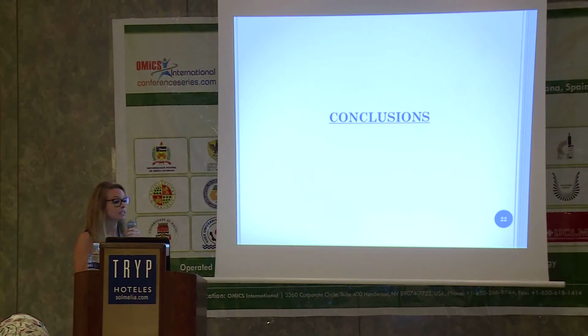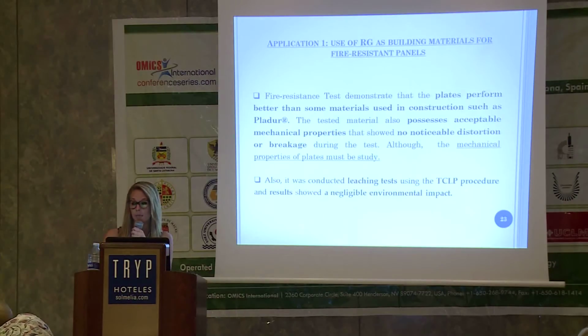So in the next slide, I will present the main conclusions for each application used. In the first one, fire-resistant tests demonstrate that the plates perform better than some materials used in construction, such as pladur. The tested material also possesses acceptable mechanical properties, showing no noticeable distortion or breakage during the test, although the mechanical properties of the plate must be studied. Also, leaching tests were conducted using the TCLP procedure, and results show a negligible environmental impact.